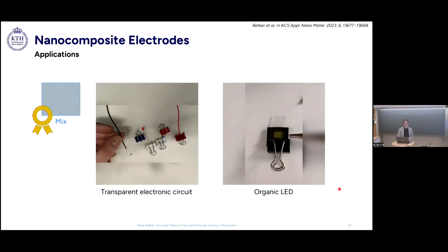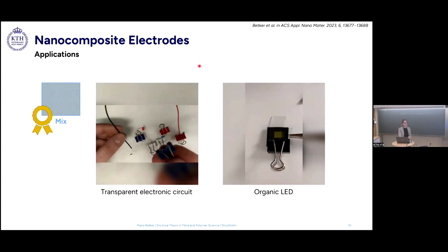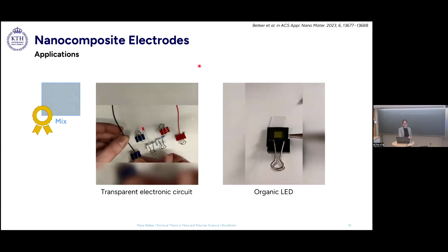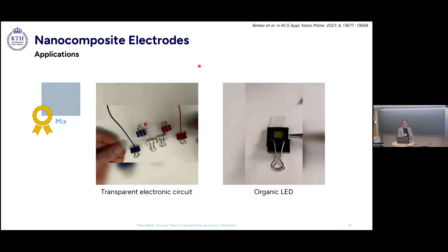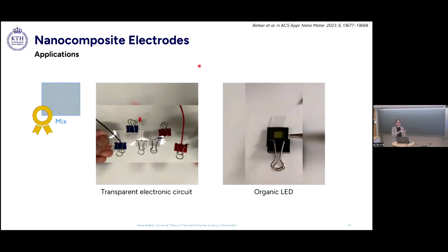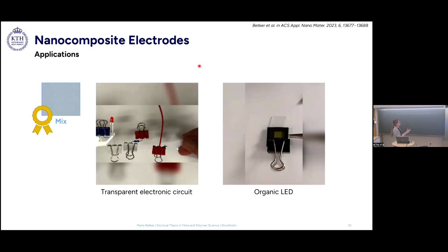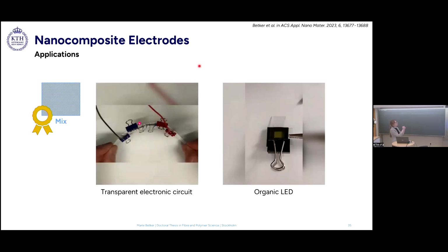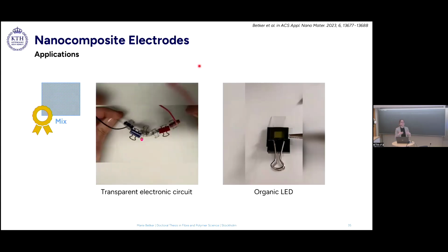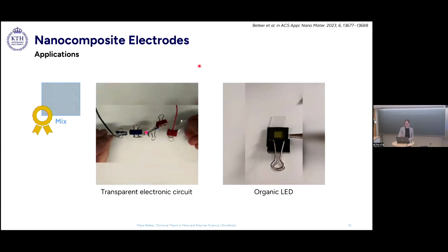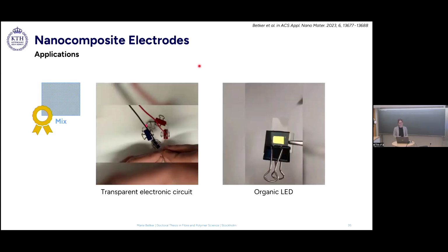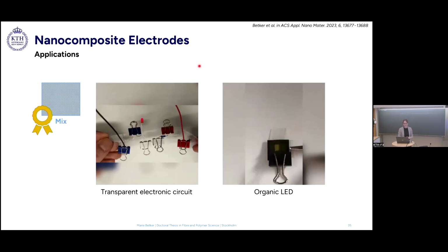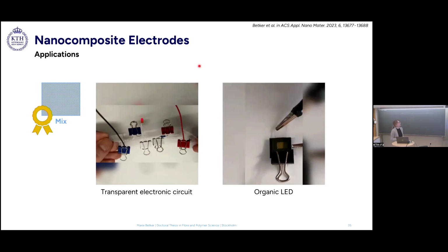on the left side. I sprayed a transparent electronic circuit. So this red thing here is a diode. And it will light up now as soon as I close the circuit. Yeah, exactly. So instead of copper wiring, in between there I sprayed the type 2 ink on a transparent PET substrate. And you can see also when I deform it, the diode keeps shining. On the right side, I used again the mixed type, but I sprayed it as an anode in an organic LED. So I sprayed it on this glass wafer, and when I close the contact, you see the LED lights up. So it works, which is nice.